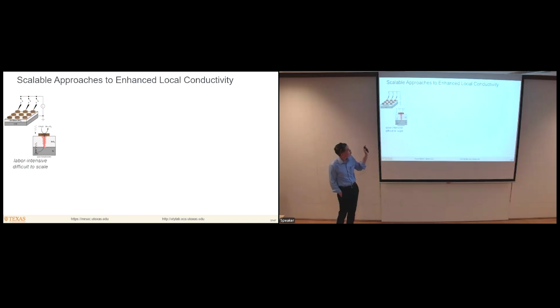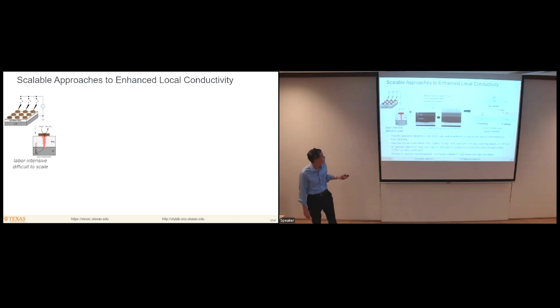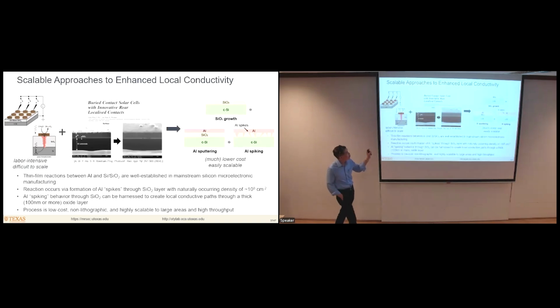So what we then thought about was, is there a way that we can take this idea of controlling the electrical conductivity through an oxide layer, but actually realize it using a much more scalable approach? To do that, we realized that we could take advantage of certain thin film reactions that occur specifically between aluminum and either an underlying silicon or silicon dioxide layer. This is something that is actually well known in semiconductor processing.